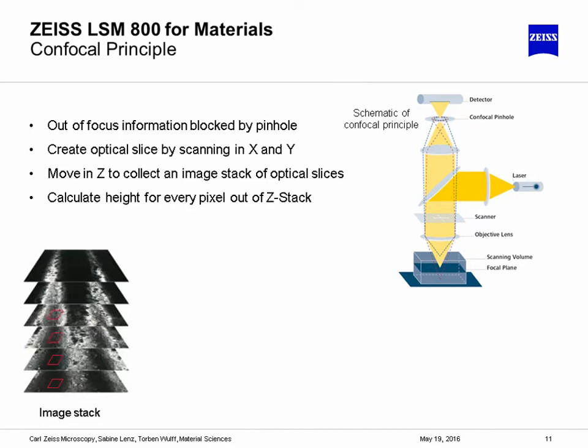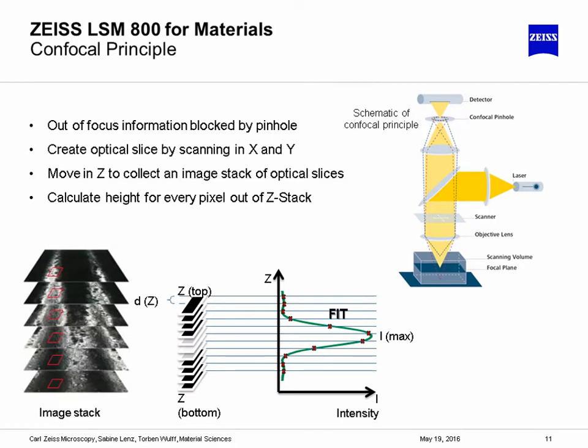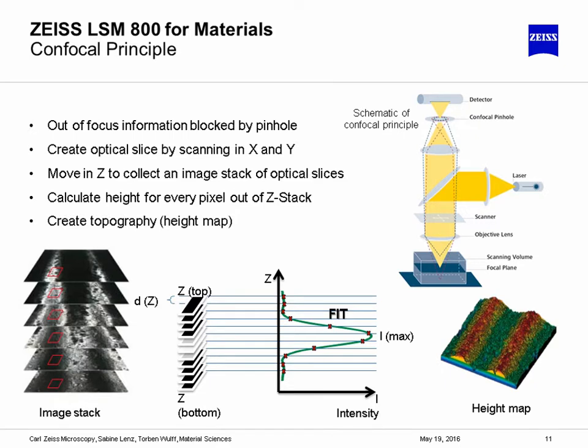And you can reconstruct that then into a surface map where you can measure things like roughness, but even begin to segment different volumes of different features. Now here you're calculating the height for every pixel that is out of the Z stack, and here, as you can see in the lower right, a height map can be produced here at a certain sample.